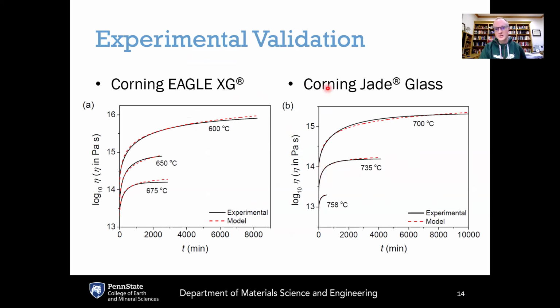These are two different display glasses from Corning, Eagle XG glass and Jade glass. What you can see is if you take a bar of these glasses and just hold them at a constant temperature. On the left here, this is taking Eagle XG glass and holding it isothermally at either 600 degrees C, 650 degrees C, or 675 degrees C. As a function of time, the viscosity here on the y-axis is increasing over time.